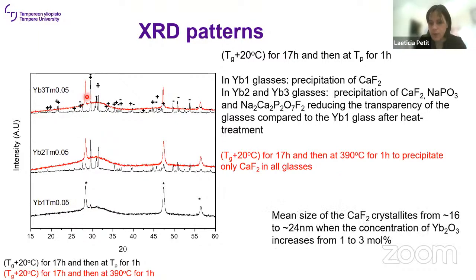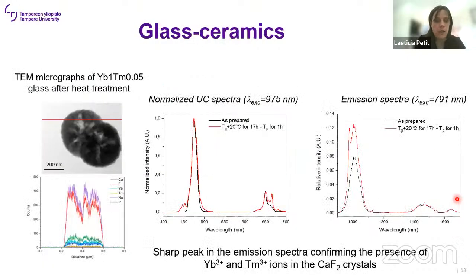Using the Scherrer equation, we found a small increase in the crystallite size from 16 to 24 nanometers when we increase the concentration of ytterbium from 1 to 3 mol%. We used a TEM, the transmission electron microscope, to look at the crystal. Here is the picture of what we found, and we confirm that it's calcium fluoride crystal, and we probably have some ytterbium and thulium in this crystal.